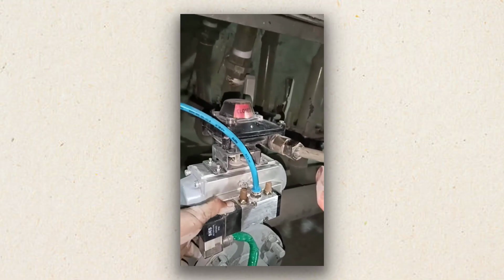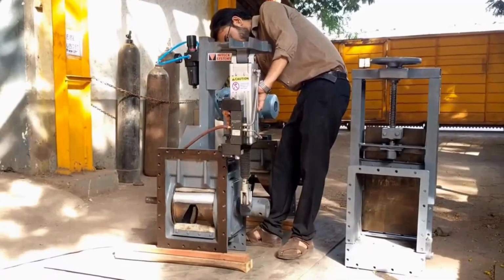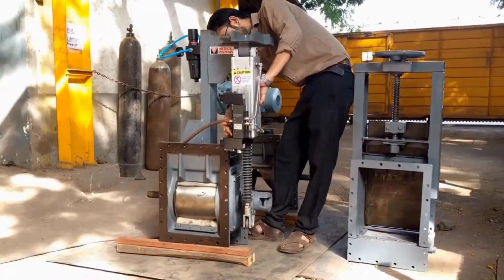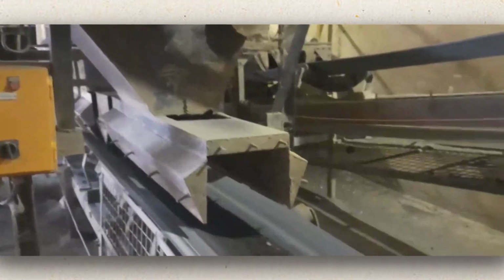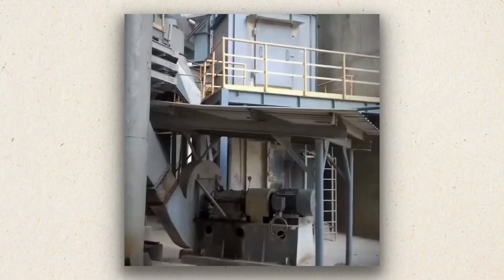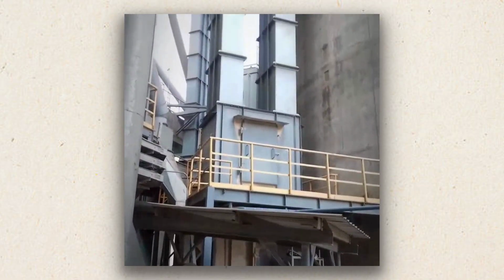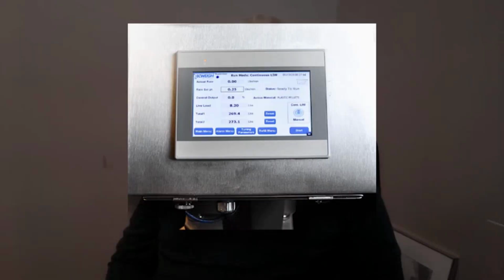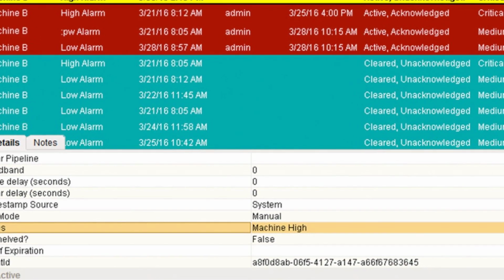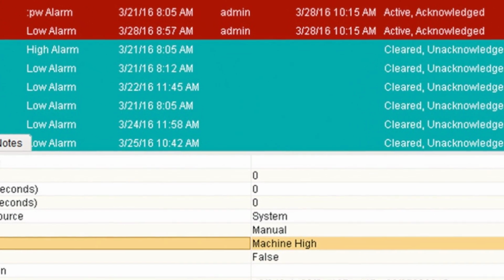Every correction triggers a physical response. If the silica content climbs, the algorithm opens the clay valve by a few percent or calls for extra corrective fines. If the LSF dips, limestone flow increases. These actions ripple through the plant as motors hum, feeders adjust, and blending silos rebalance.